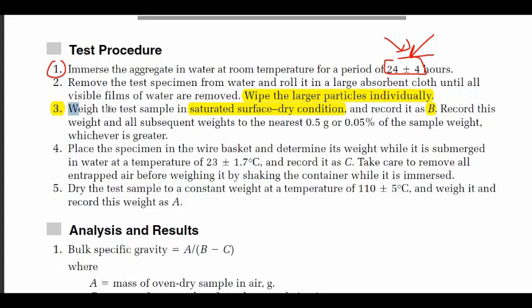So here, step number 3, we're going to weigh the test sample in a saturated surface dry condition. Okay, saturated surface dry condition. After making step number 2, we reach the saturated surface dry condition and record it as B. Number 4, place the specimen in the wire basket and determine its weight while it is submerged in water at a temperature of 23 plus or minus 1.7 Celsius and record it as C. So this is the sample with water. Then take care to remove all entrapped air before weighing it by shaking the container while it is immersed. This is something we're going to see in the video. We're going to shake the container while it is immersed.